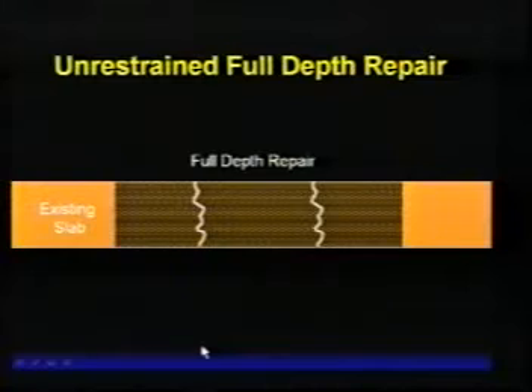Full depth repairs are special. Anytime we're doing horizontal repairs, the selection of the material is really critical for low shrinkage because we have no restraint for any type of movement that takes place. But we do have the boundary of those repairs that forms a fixed point. So any shrinkage that takes place will manifest itself generally in some type of cracking. So the selection of the material for reduced shrinkage is very important for full depth repairs.